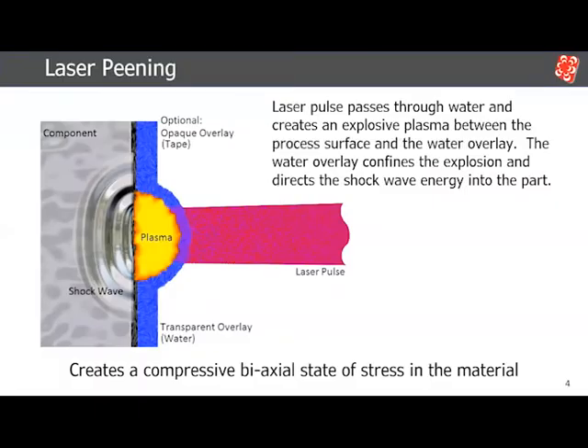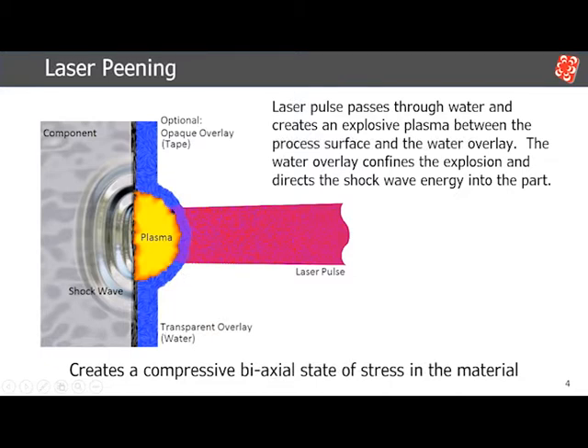Very briefly, talking about the laser peening process. In laser peening, we use a pulsed laser. When that laser hits the surface, it generates a plasma. The transparent overlay is what confines the plasma — transparent because it is transparent to the laser, meaning you don't lose much energy going through it, and mainly we use water for it. The transparent overlay confines the plasma, pushing the energy from the plasma into the material, creating a shock wave. That shock wave is what generates the compressive residual stresses, which I explained yesterday provide great benefits from the laser peening process.